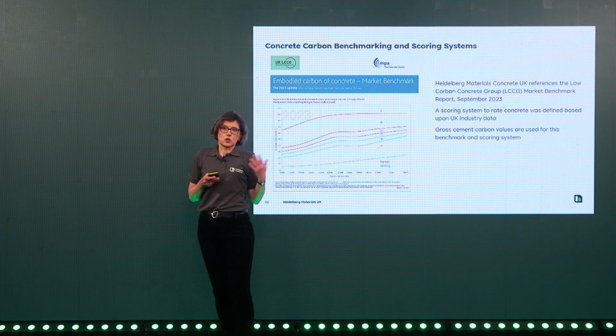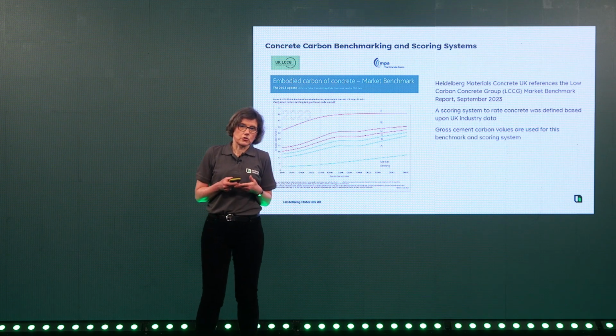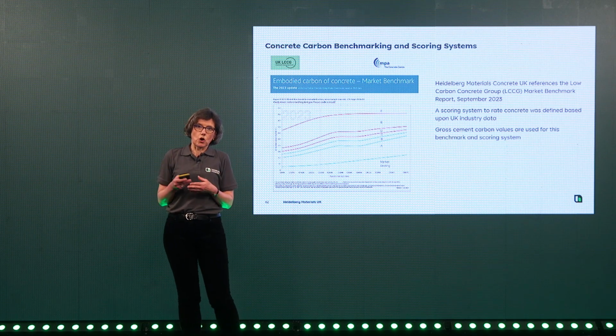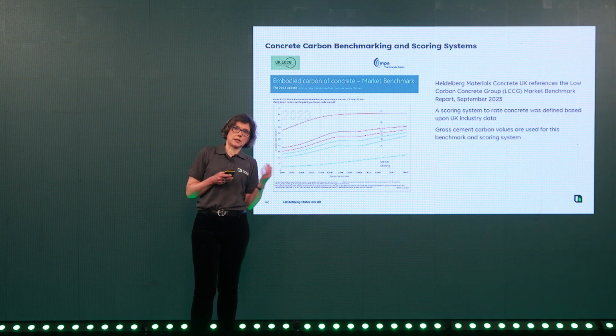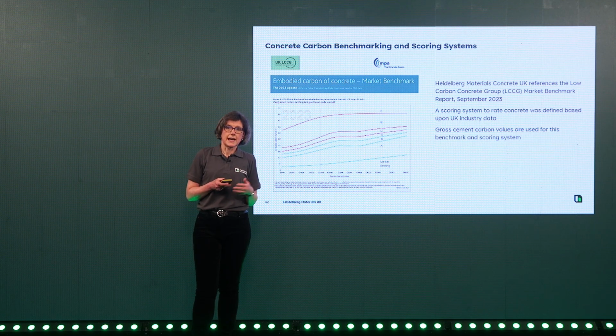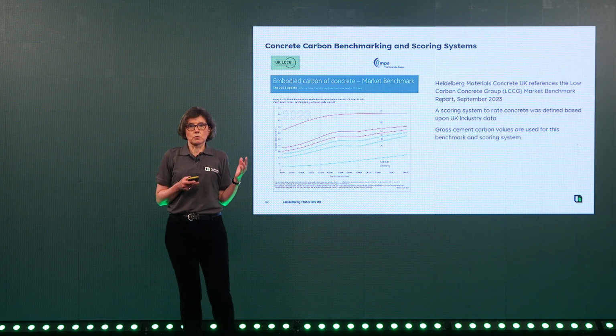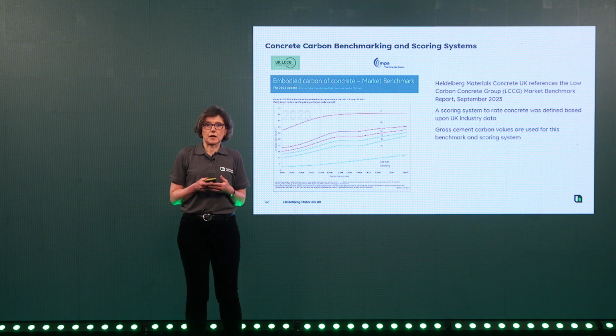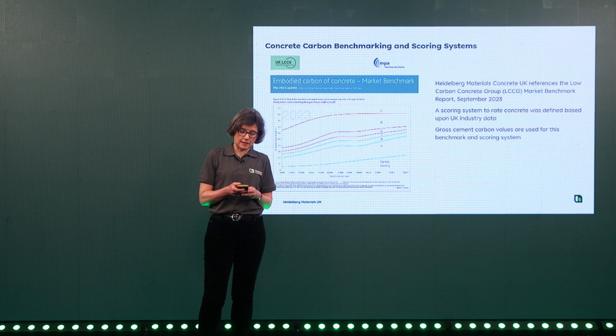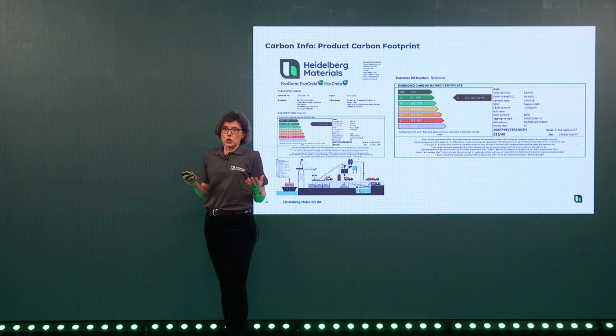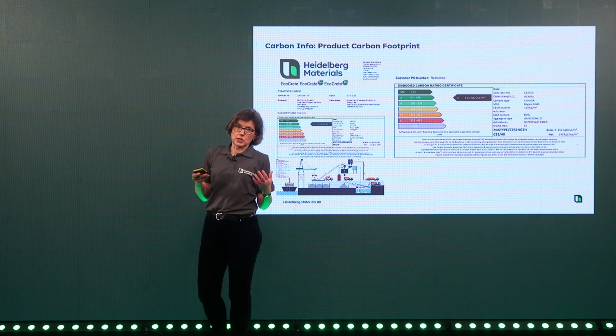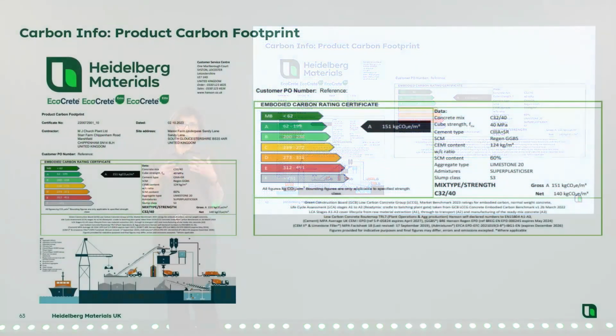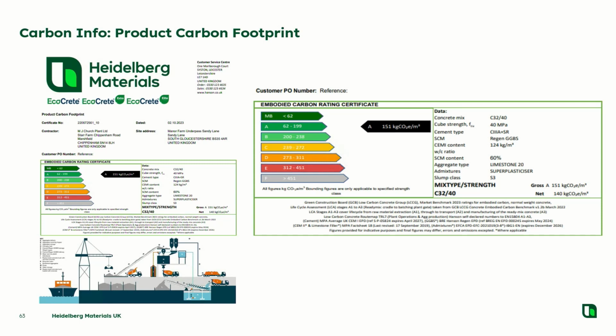This scoring system was devised on industry data, and in fact it includes a lot of our own concrete data which was inputted to get to these benchmarks. And this system again uses gross cement carbon values, and that's why clearly we also can compare our data against this particular graph. So if you order concrete with us at the quotation stage now, we can give you an indication of the embodied carbon we expect for the particular concrete you're ordering.